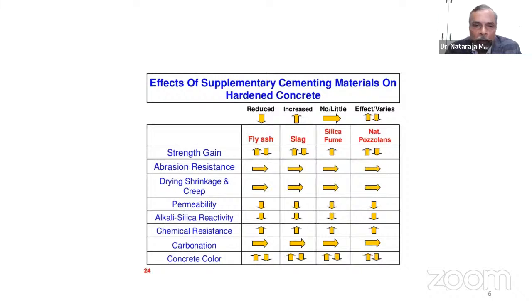And also, if you see the hardened concrete, the strength gain. And of course, with some supplementary materials, depending on the quality and the pozzolanicity of the material, sometimes the strength might decrease. But if the supplementary materials are of quality type, definitely the compressive strength, or even the other related strengths, because most strengths are primarily related to compressive strength, will increase. Addition of silica fume and metakaolin all the time increases the compressive strength, and that is the reason addition of 10 to 15% of silica fume or even metakaolin gives a substantial improvement in performance as far as high-strength concrete is concerned.